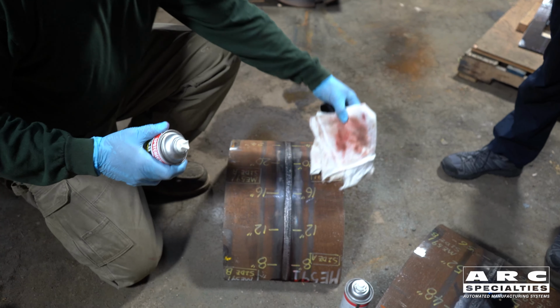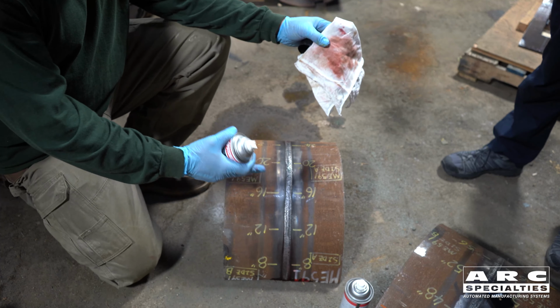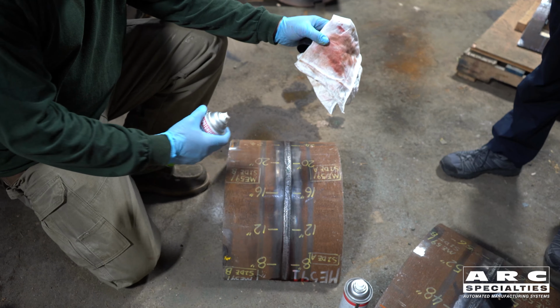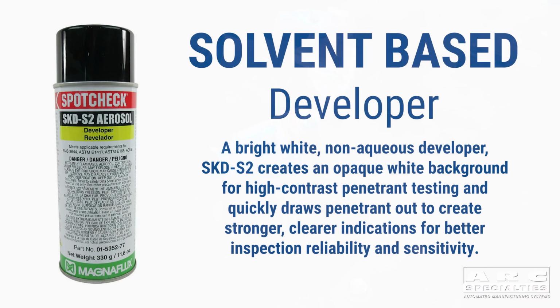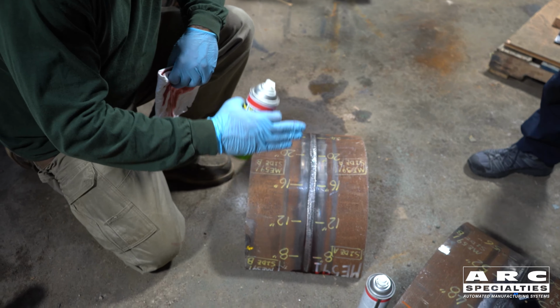All right, our 10-minute evaporation time for our post-clean after the dwell time of the penetrant. We use some SKD S2 developer. What this does is give a contrast for the red to stand out so we can see with our eye.